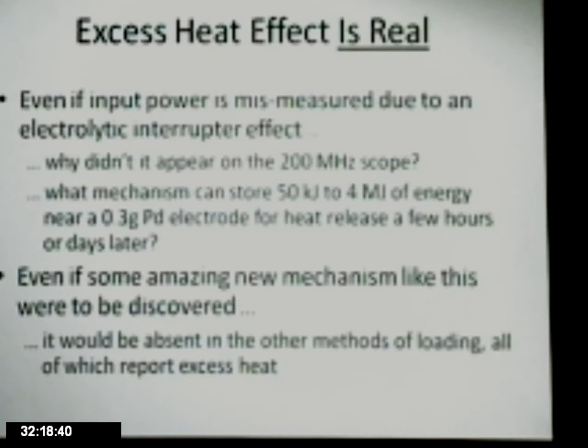Okay, even if the input power is mismeasured due to an electrolytic interrupter effect, why didn't it appear on the scope with much greater bandwidth? And what mechanism can store, say, 50 kilojoules to 4 megajoules of energy near a 0.3 gram, 2 millimole or so, palladium electrode for heat release a few hours or even a couple days later? Because this heat release typically occurs many hours to a couple days after the steady loading conditions have been achieved, for reasons, again, that aren't well understood.